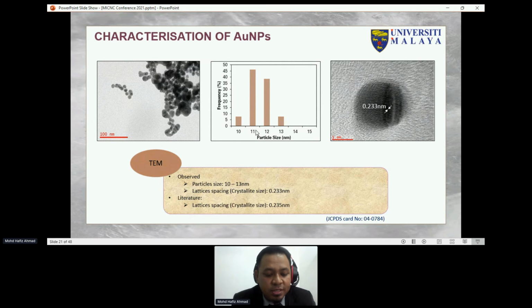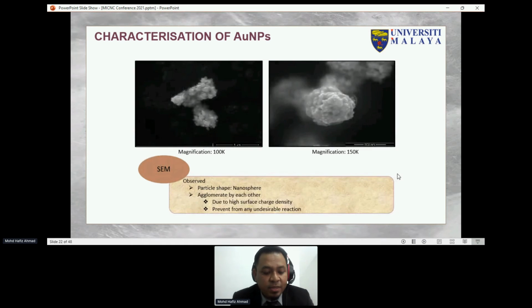The size distribution of my synthesized gold nanoparticles shows the particle size is around 10 to 13 nanometers. And then the high resolution image of the lattice fringes of gold nanoparticles shows the spacing is 0.233 nanometers, almost similar to the literature. For the same image, the gold nanoparticles are formed in nanosphere shape and agglomerate with each other. Based on all data and comparison with literature, the gold nanoparticles that I synthesized are 10 to 13 nanometers in size and nanosphere in shape.